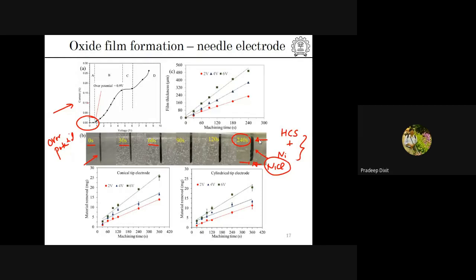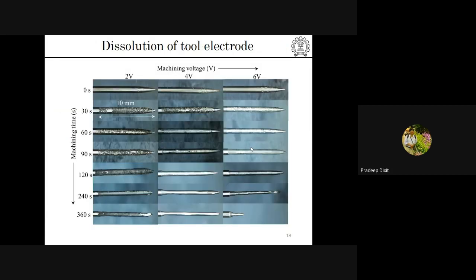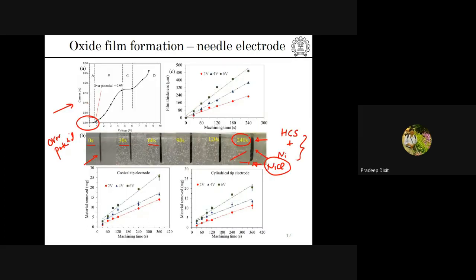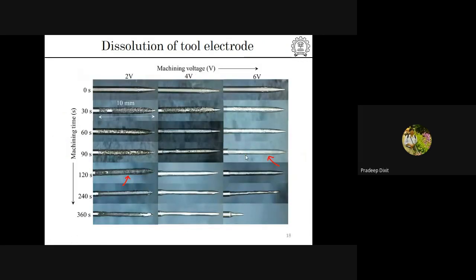So that is one of our findings: if you do not remove this nickel coating, it is going to cause problems during the machining process. Let me show you the results. We have taken 3 values of voltage, 2 volt, 4 volt, and 6 volt, and these are some of the pictures at different time intervals. You can see that in some cases the surface is very smooth, and in some cases the surface is black. This black film is the same nickel chloride film. So it indicates that if you do not remove the sludge efficiently, you are going to have a problem during the electrochemical machining process.